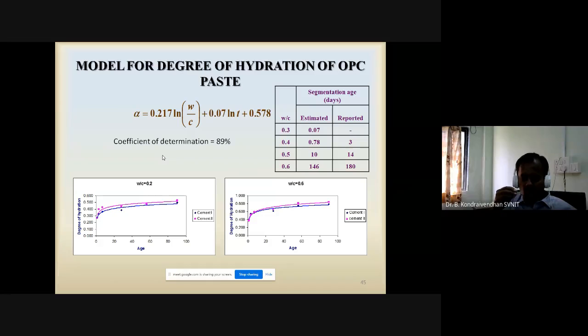Over the period of time, what is happening? The capillary pores are getting segmented, because hydration is a continuous process. The capillaries become segmented, blocked by the gels. More and more CSH gels are forming, and then the interconnectivity is affected or blocked. That is called segmentation. So one can also calculate the segmentation age of the pores. By equating the capillary entry radius to 0, you can calculate the segmentation age for different water cement ratios. We estimated the segmentation age for 0.3, 0.4, 0.5 and 0.6,